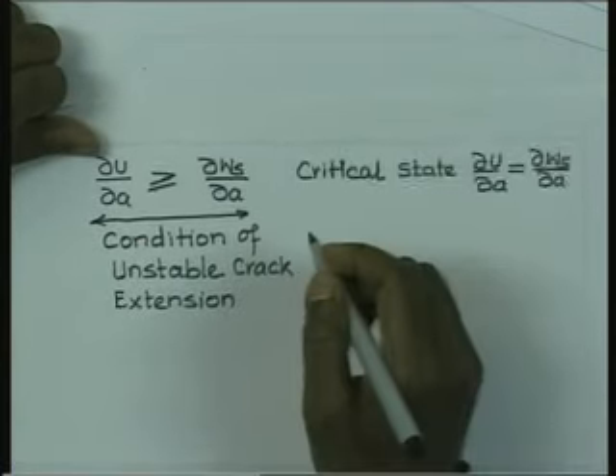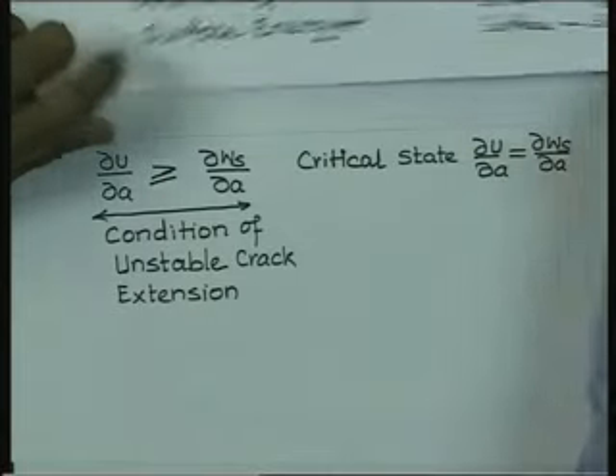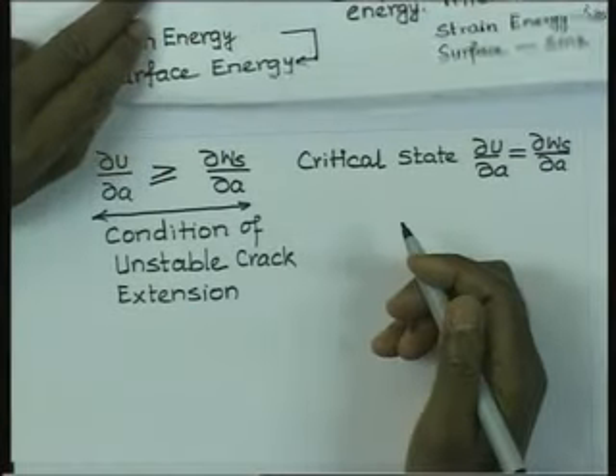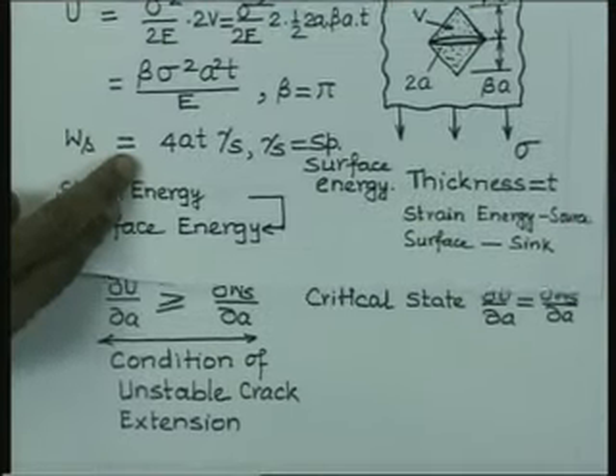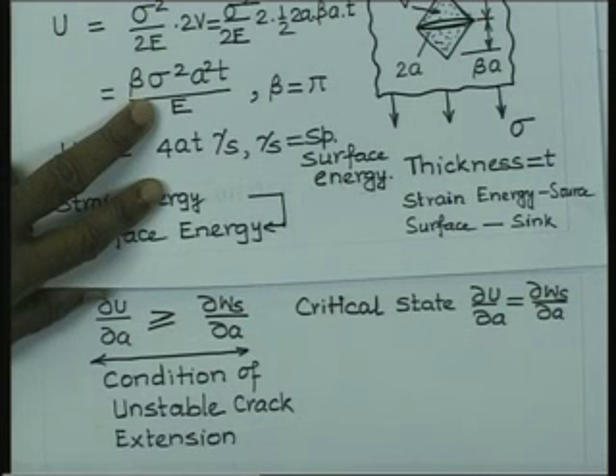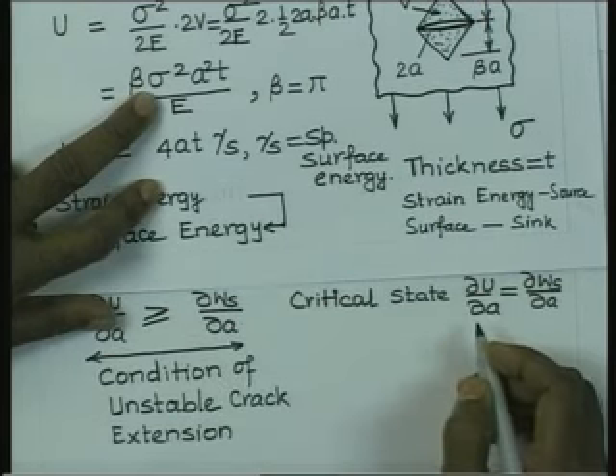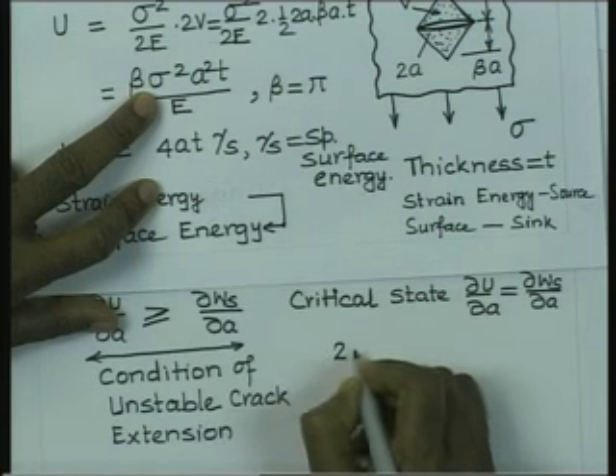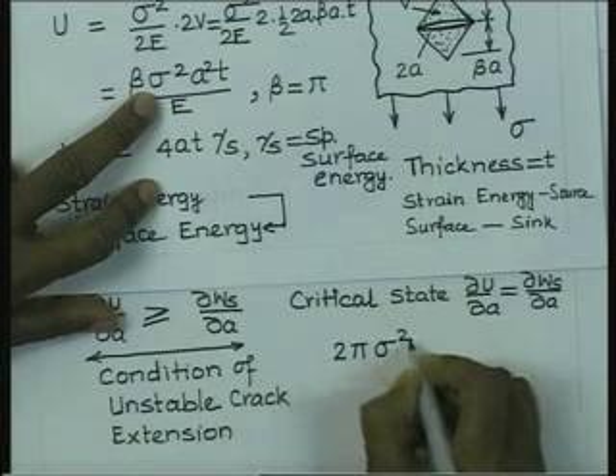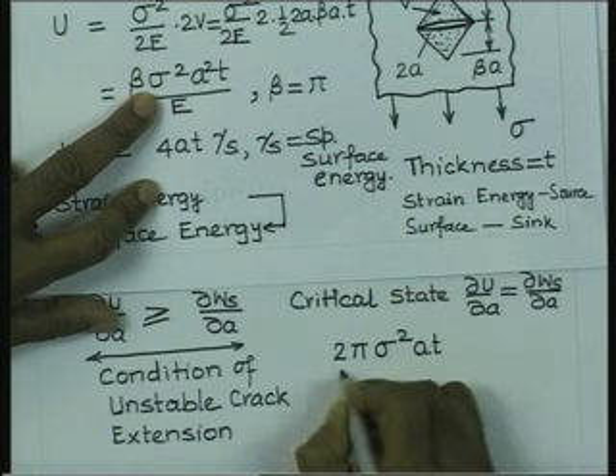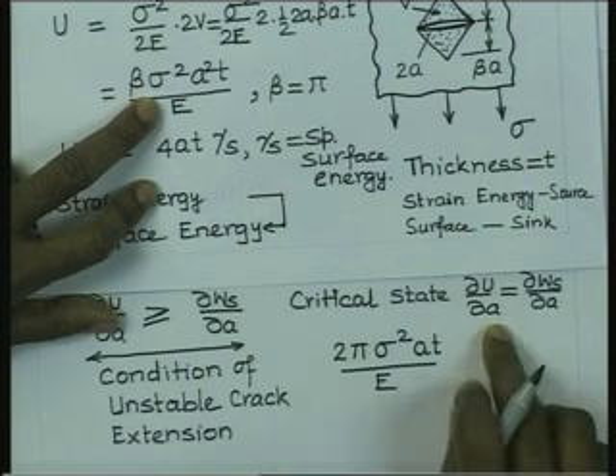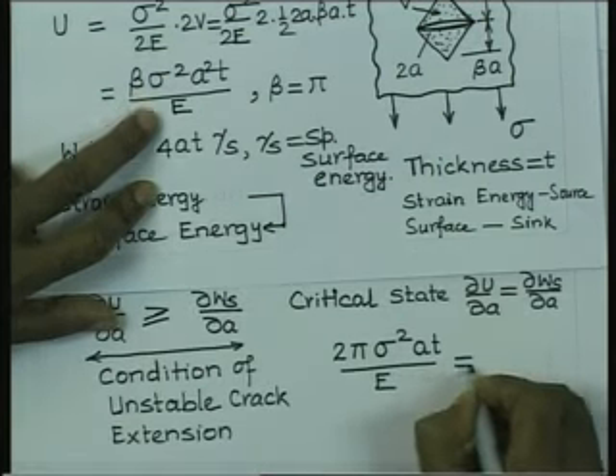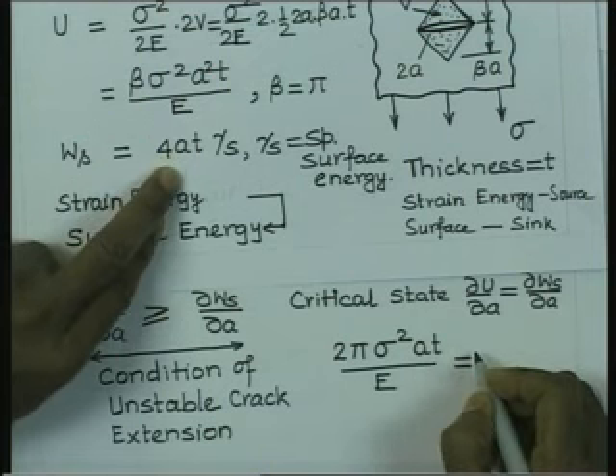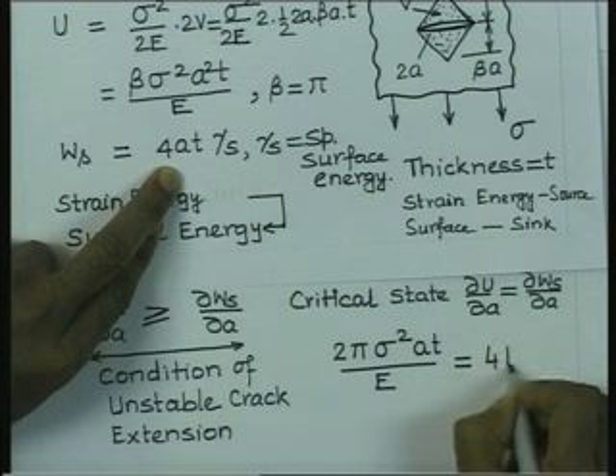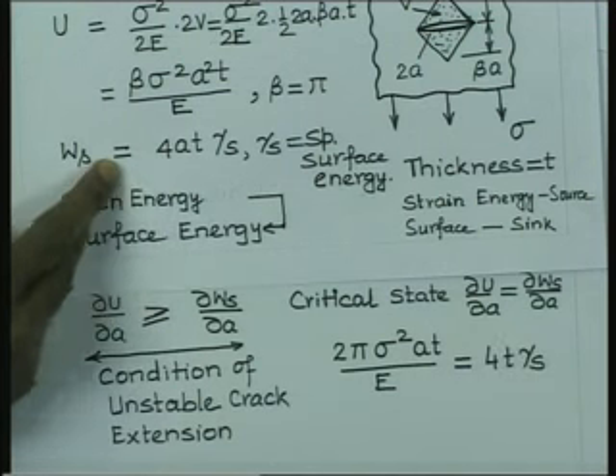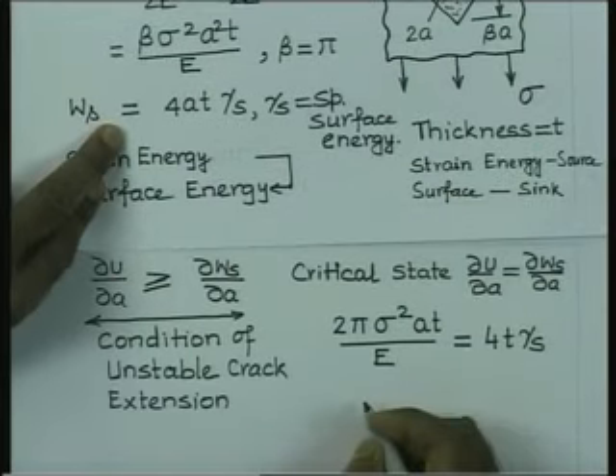So, we can now write the value of delta U by delta A. Our U was pi sigma square a square into t by E. So, if we take the derivative, it is going to be twice pi sigma square a t by E, that is delta U by delta A, and if that is equal to delta Ws by delta A, which is nothing but 4 t times gamma s. So, this is the condition for the onset of extension.